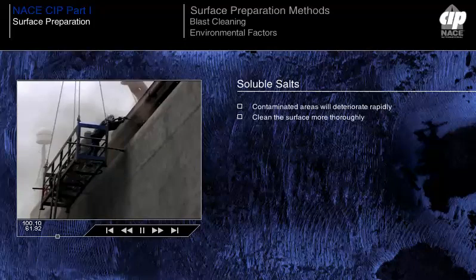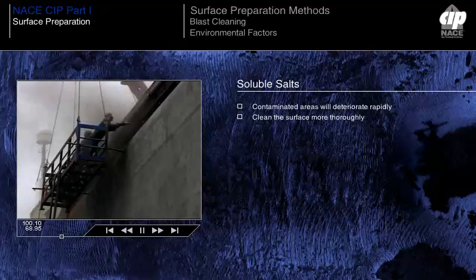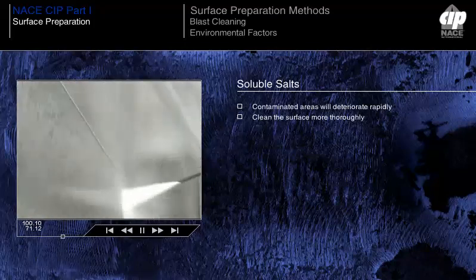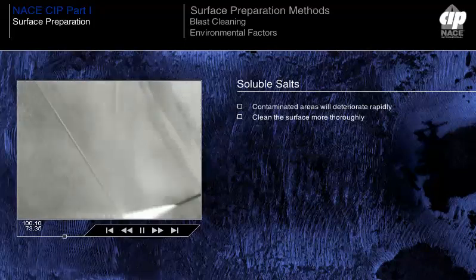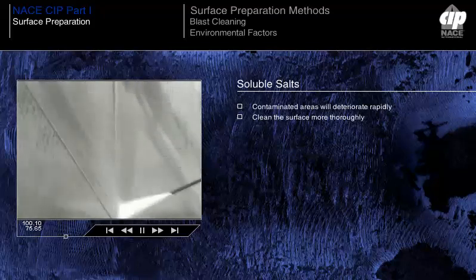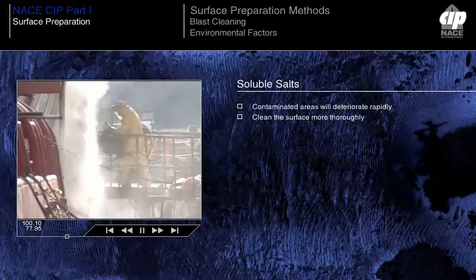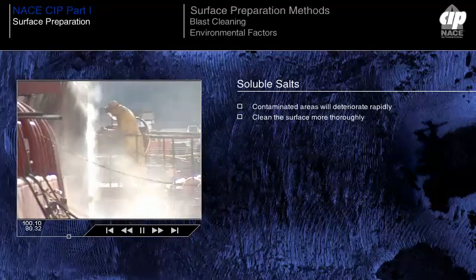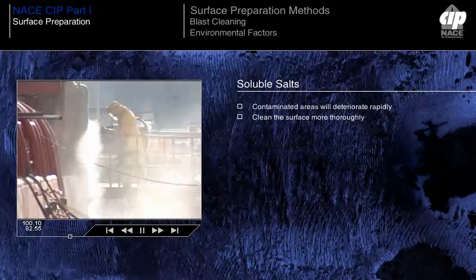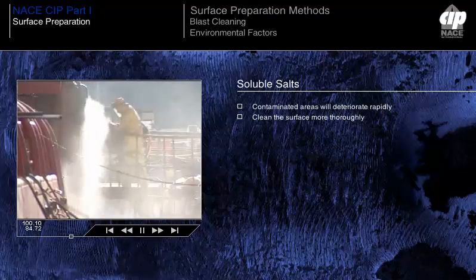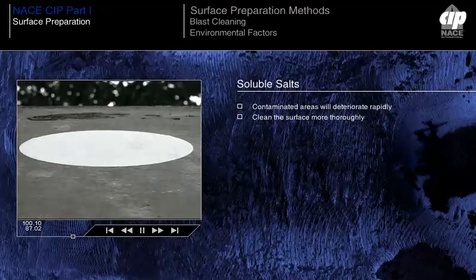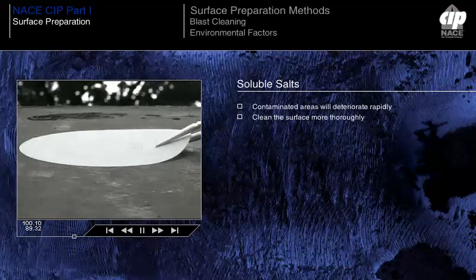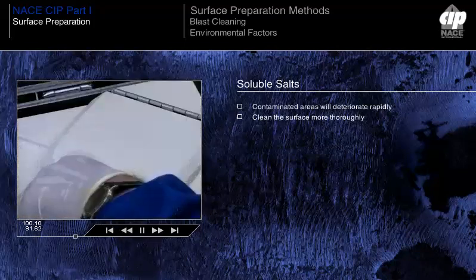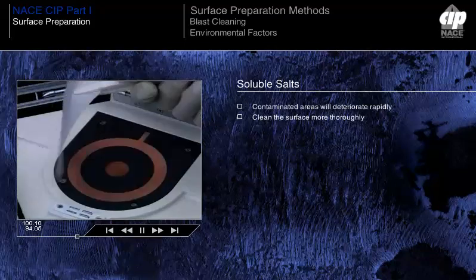To remedy the problem, the surface should be cleaned more thoroughly. Further blast cleaning may be effective in some cases, but better success may be achieved by washing using high-pressure wash equipment. Water jetting may also be effective to remove heavy contamination. Surface preparation in these cases should be followed by testing for soluble iron, ferrous salts, and/or chlorides, to ensure that remaining contamination is below critical levels.